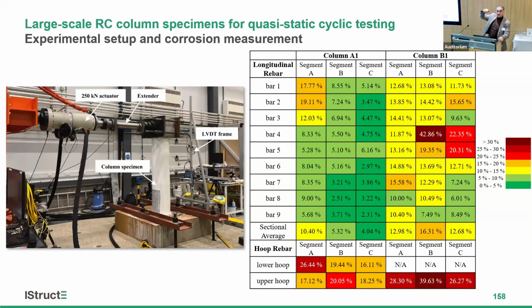The bridge pier is under cyclic loading, because when you have an earthquake on a bridge with multiple spans or a single bridge pier, the earthquake has two components. For the perpendicular component, the bridge piers behave like a vertical cantilever beam, with predominantly flexural behavior. We put some DIC speckle here to measure the moment curvature, and we have LVDTs to measure the horizontal deformation. I also added a couple of accelerometers and did some hammer tests, which I'm not presenting here, to get dynamic properties that degrade and potentially can be used for health monitoring. That's out of scope for today, but it's available in the papers.